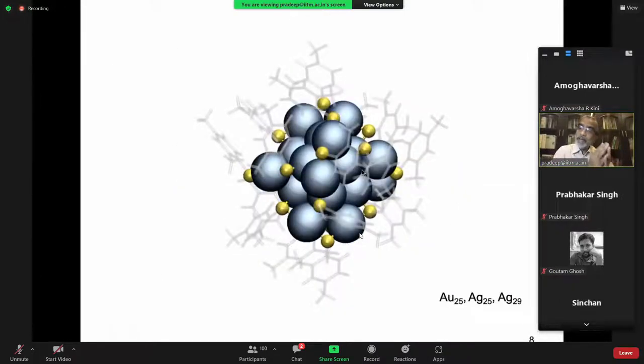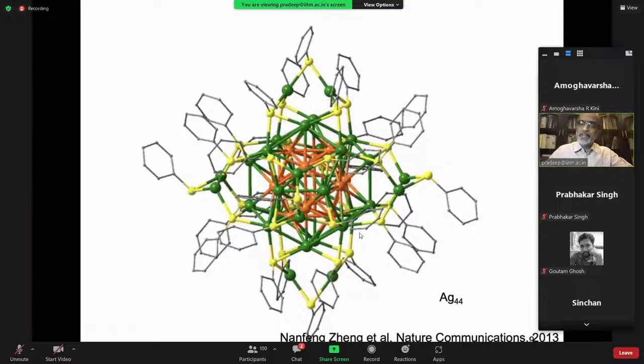Now, you have a number of other similar clusters. And an equivalent one is silver 25. And if you put the atomic diameter or radii and redraw this structure, this is like a piece of metal. And the dark, larger ones are the gold or silver atoms. So you see a piece of this gold metal. You have a number of other such clusters, as I just mentioned.